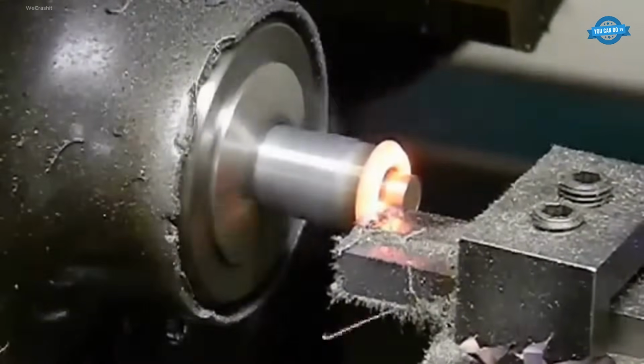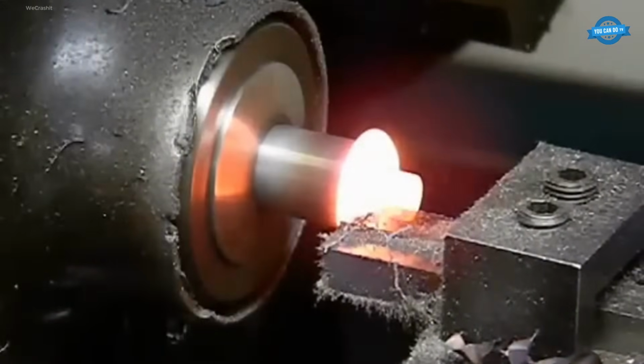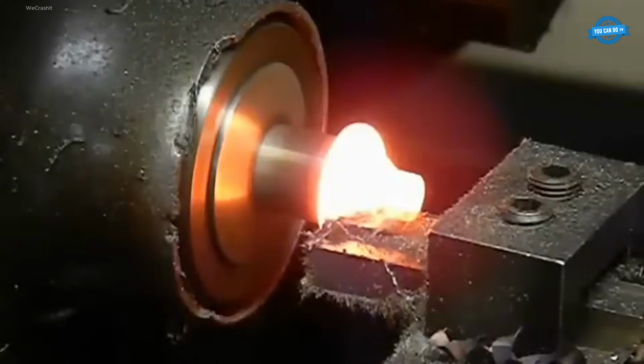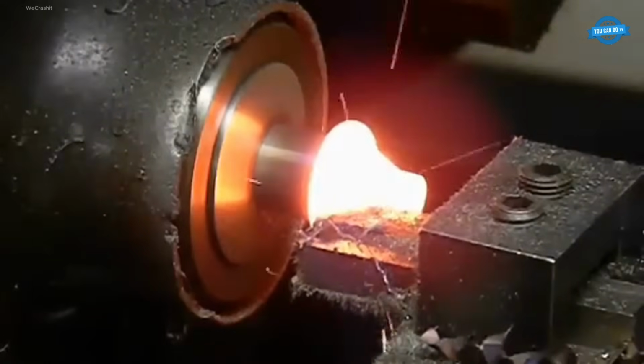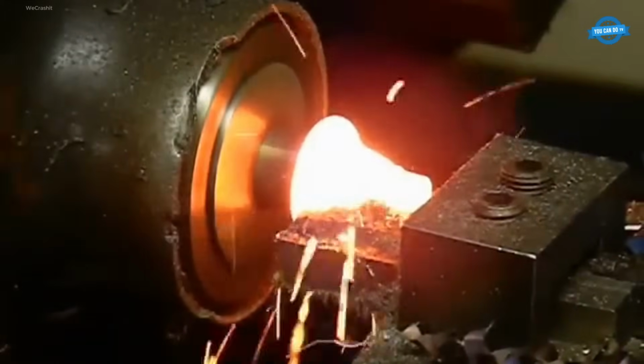Each tool was tested to destruction. Only 2 out of 12 tool bits completed cuts on more than 10 parts, showing minimal wear and the potential to continue. The next best tool failed on the 4th part. Tool performance varied significantly under identical conditions.